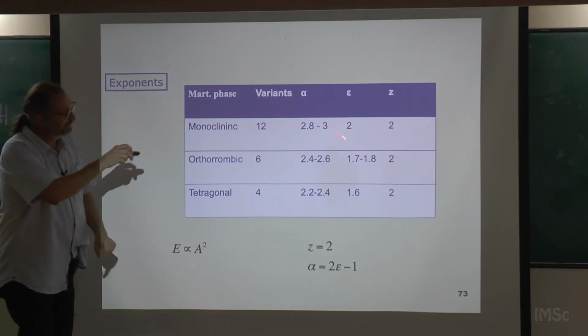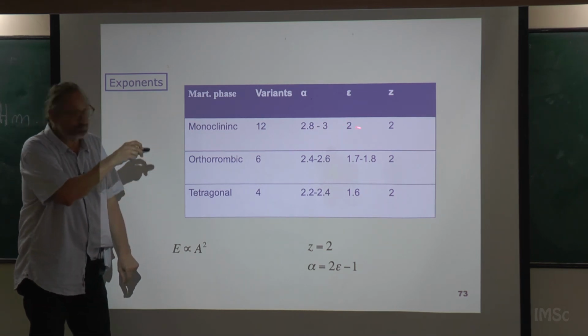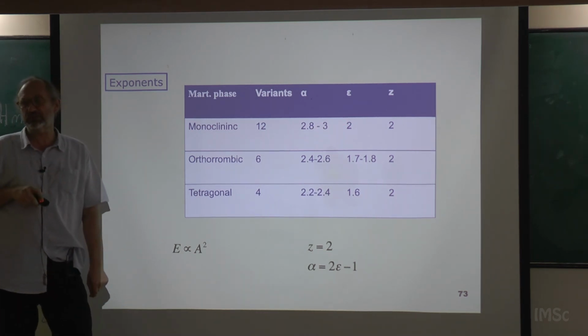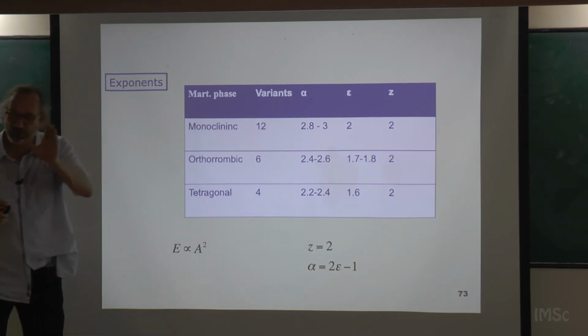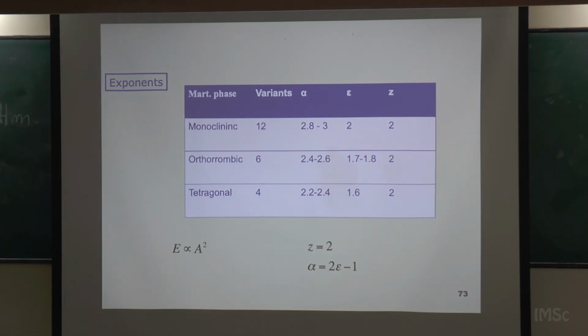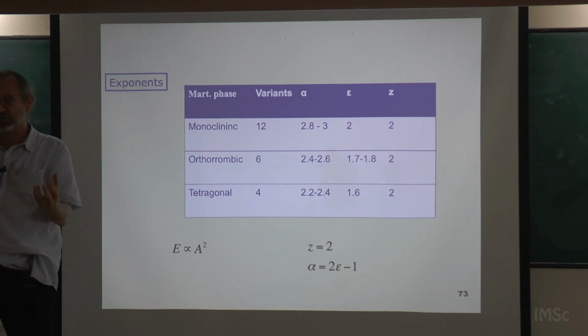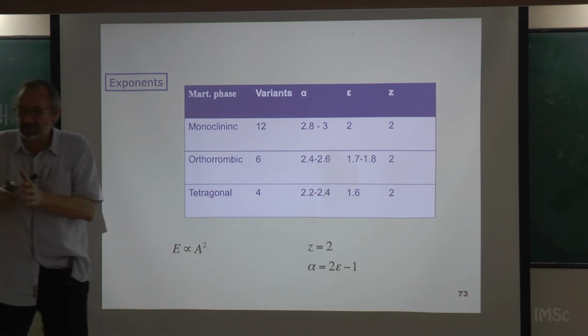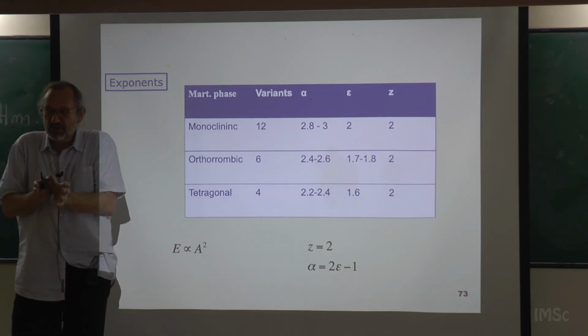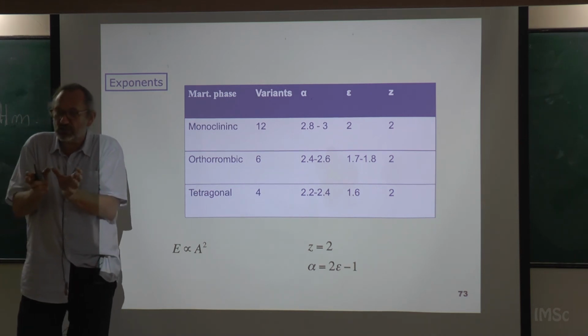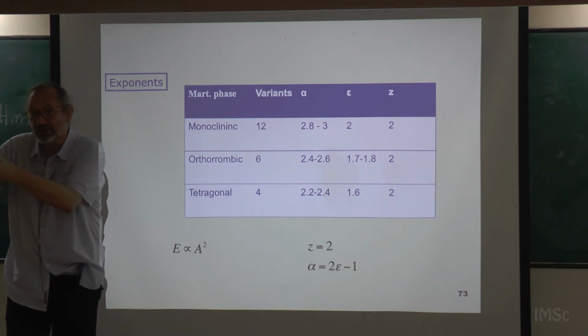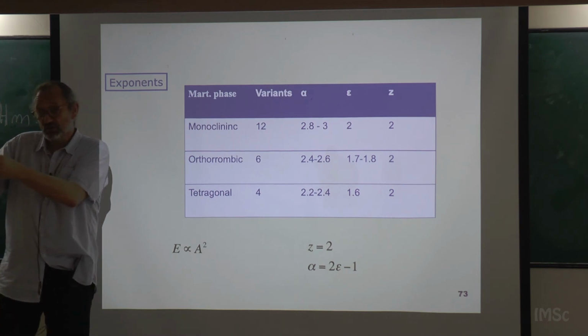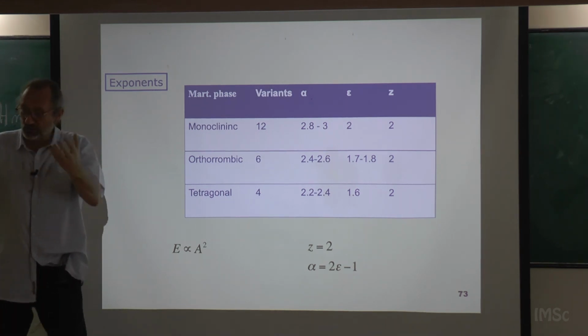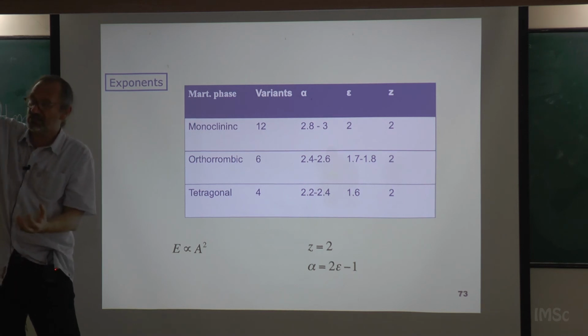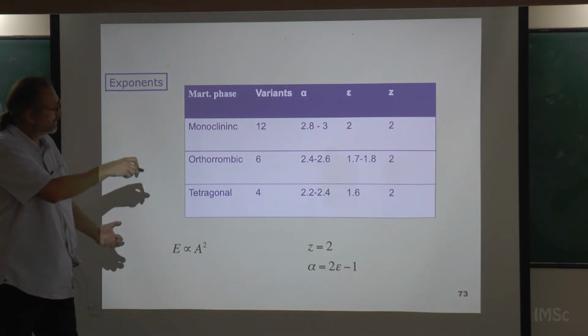But okay, anyway, you see the exponents are not the same; the exponents depend on the symmetry of the low temperature phase. Why is the exponent changing? Because the exponent has to do with the relative weight of the big avalanches to the small avalanches. When the system has more variants, it finds more paths to transform. It's easier to transform, finding smaller regions without having the big avalanches. So then you have more small avalanches and fewer big avalanches. This means a larger exponent.